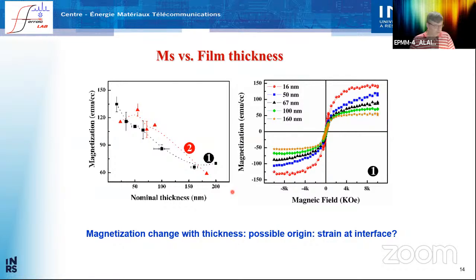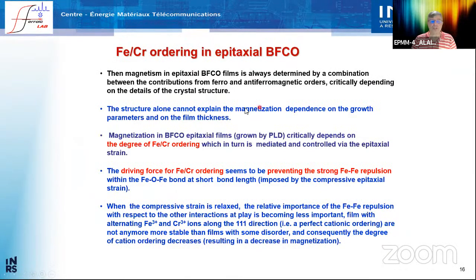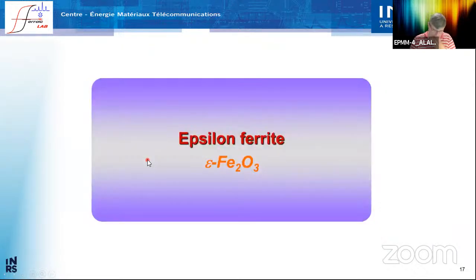So that was for the BFCO film. As I said, we believe that the chromium is shielding the strong interaction between the iron-iron, and that's what is creating the ordering. The other material I want to speak about is epsilon ferrite, and this is a potentially multiferroic